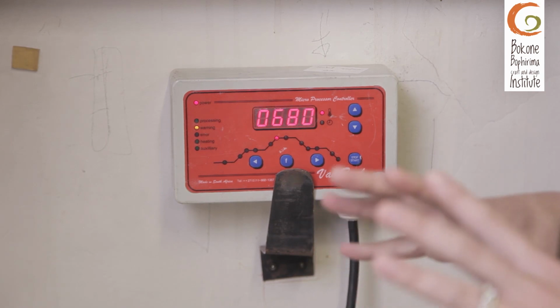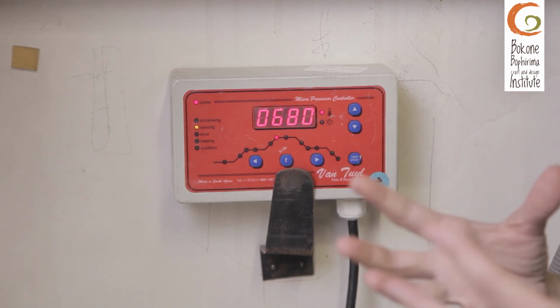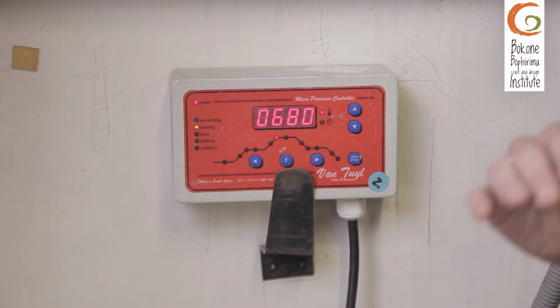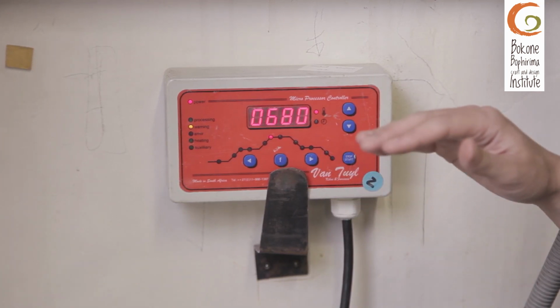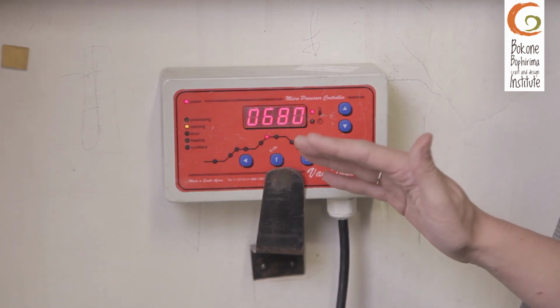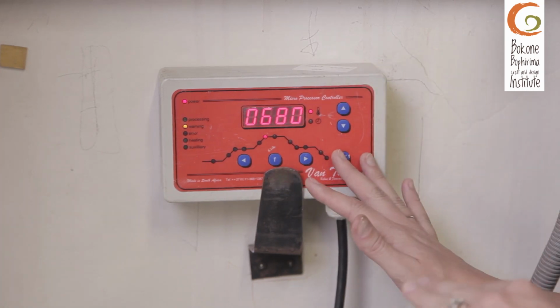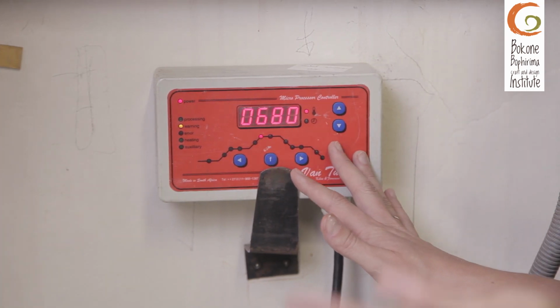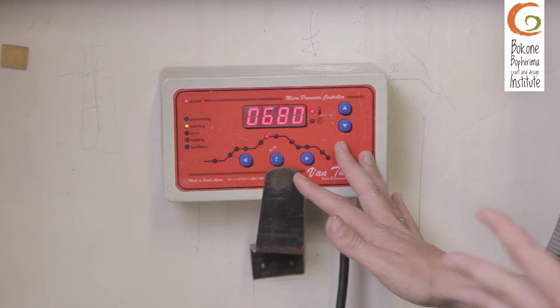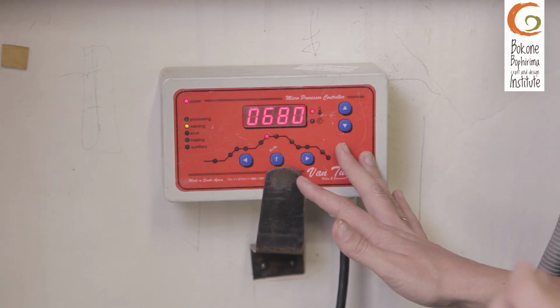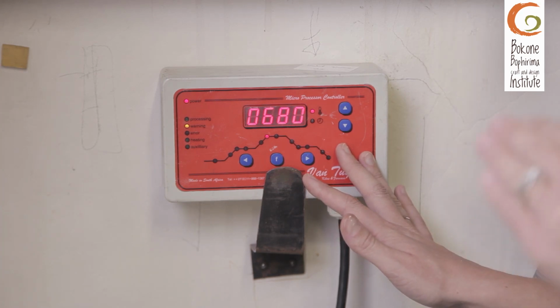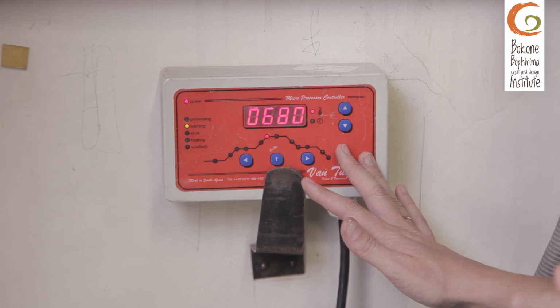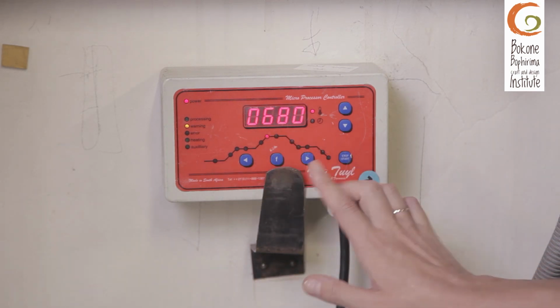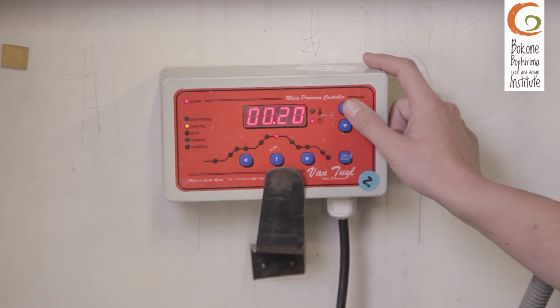So this is a nice temperature to use and hold the glass if need be, and we need to hold the glass there, for instance, for an hour, half an hour. Rather hold it at a lower temperature of 680 than trying to ramp it higher, because anything higher than 700, especially with float glass, we tend to get devitrification, that crystal layer on top. So if we can keep our top temperature lower than 700, we will be less chance of devit. So I'm going to hold my glass there for 30 minutes.